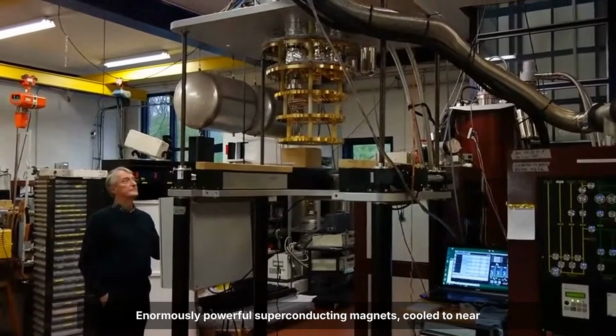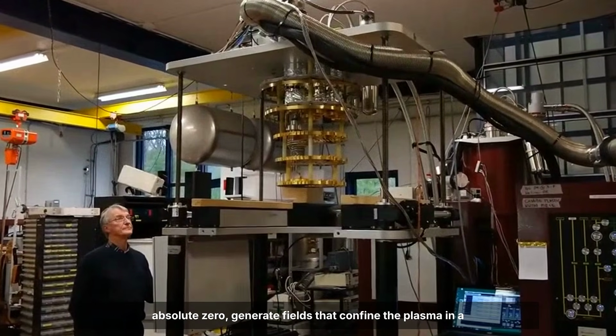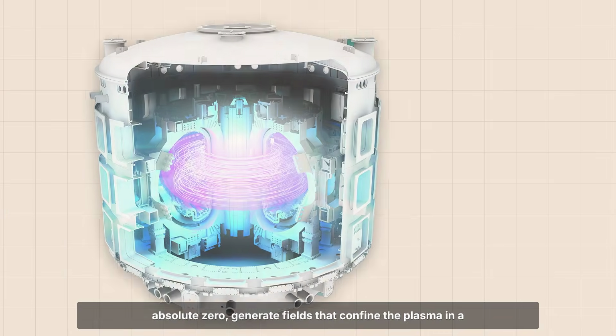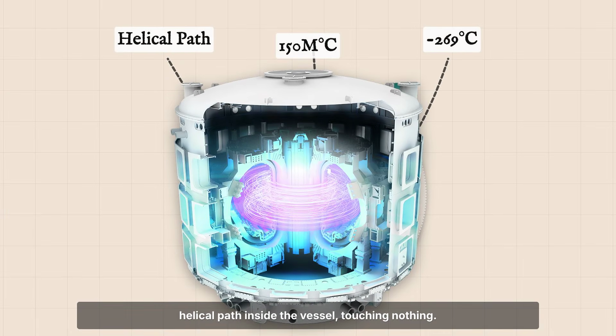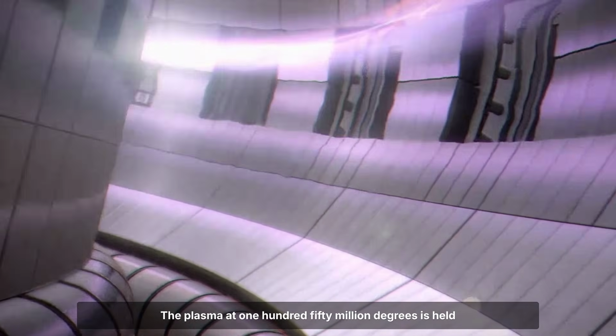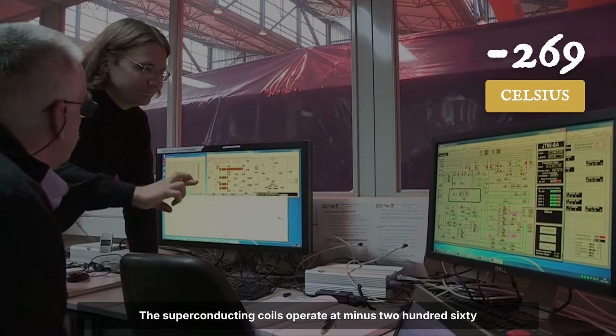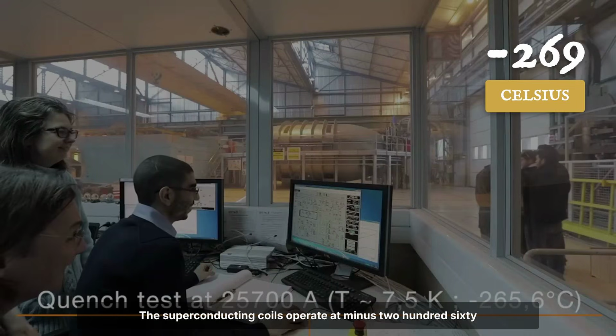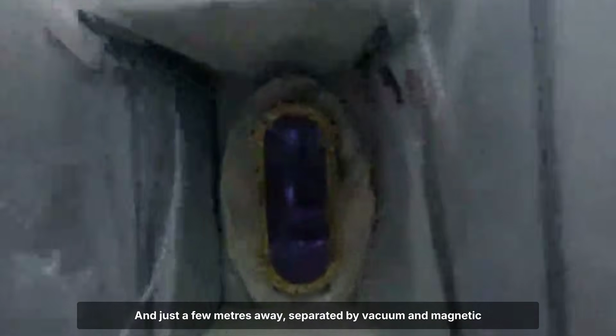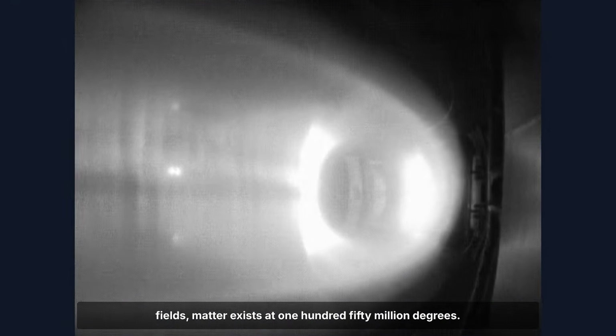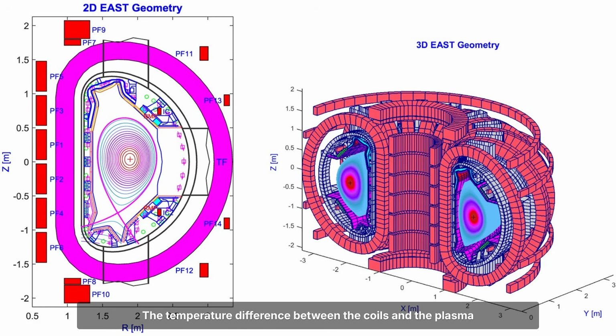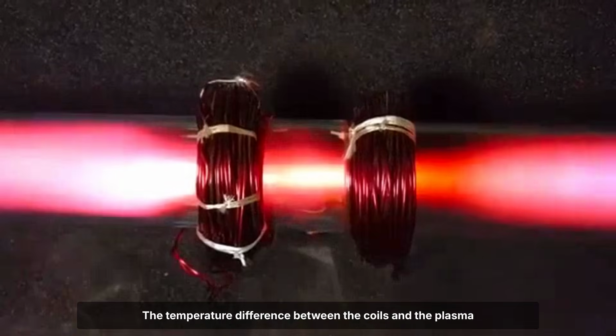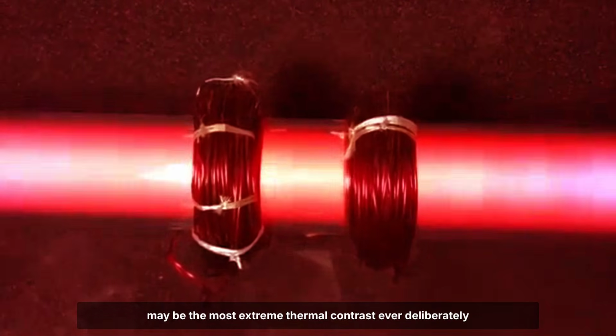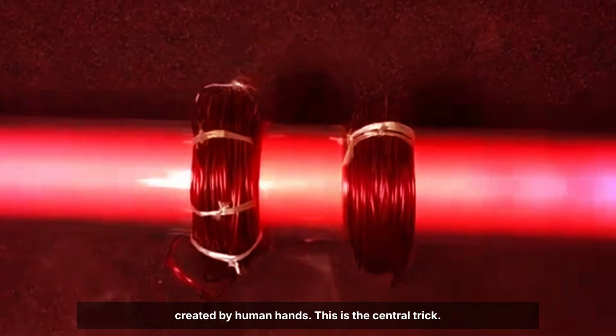Enormously powerful superconducting magnets cooled to near absolute zero generate fields that confine the plasma in a helical path inside the vessel, touching nothing. The plasma at 150 million degrees is held inside a magnetic bottle. The superconducting coils operate at minus 269 degrees Celsius, 4 degrees from absolute zero. And just a few meters away, separated by vacuum and magnetic fields, matter exists at 150 million degrees. The temperature difference between the coils and the plasma may be the most extreme thermal contrast ever deliberately created by human hands. This is the central trick.